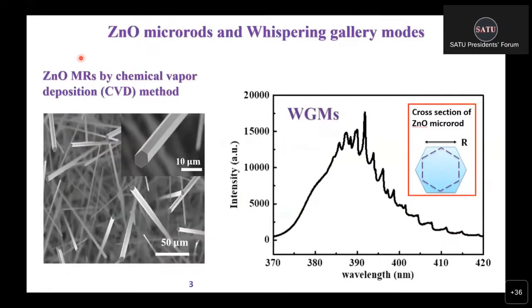The microstructure used here is zinc oxide microrods. We synthesize these rods by the CVD method on a silicon substrate. The inset figure shows the cross-section of a single zinc oxide microrod. The shape is hexagonal, which corresponds to the wurtzite structure of zinc oxide. We observe many optical modes in the spectrum. This is because the optical photons can propagate inside the microcavity by total internal reflection, and because the optical loss of total internal reflection is very low, the optical modes become very sharp.